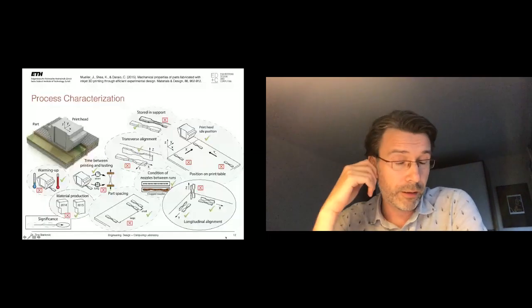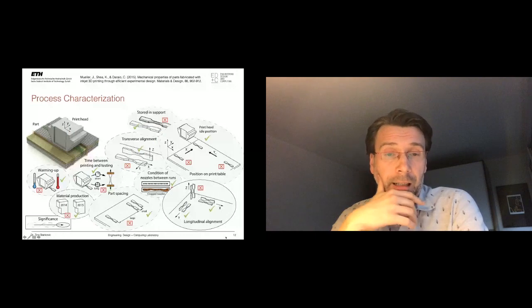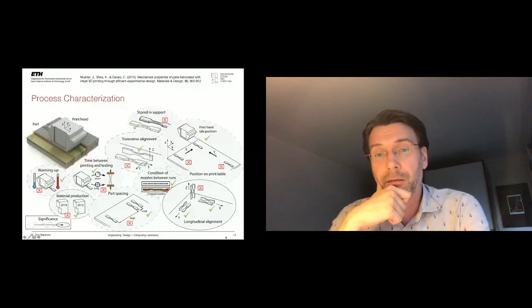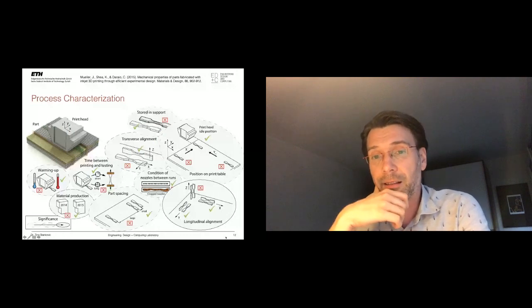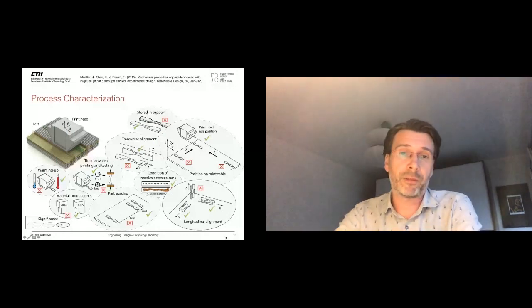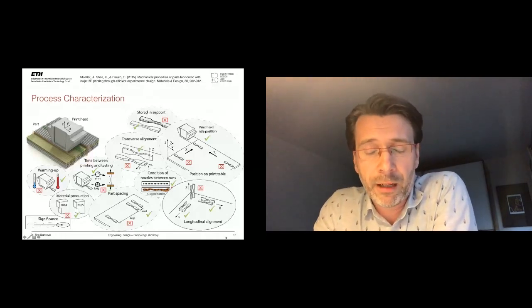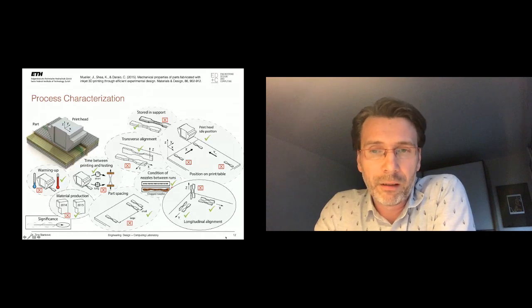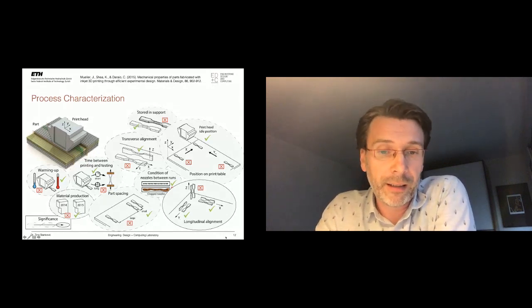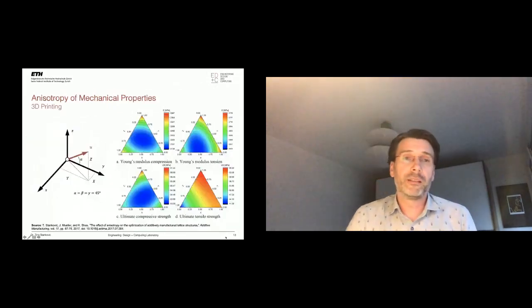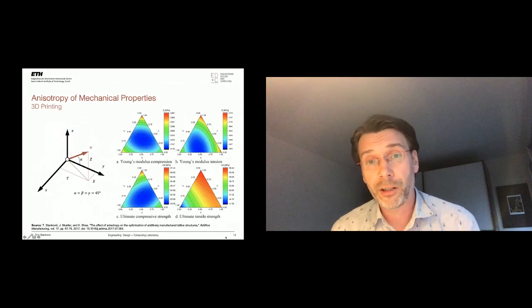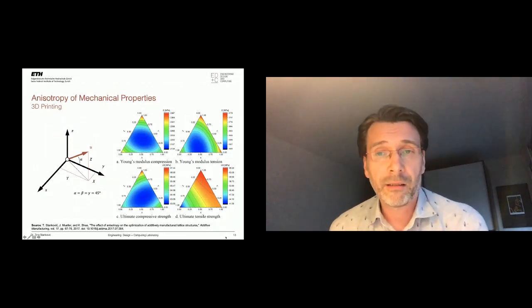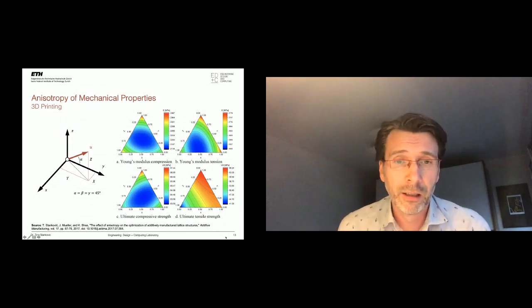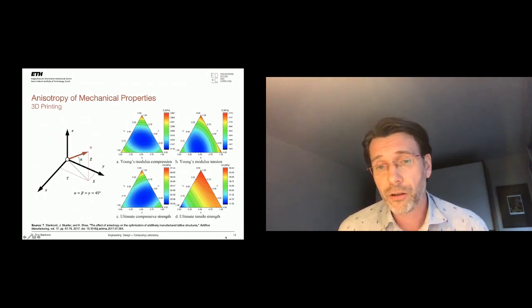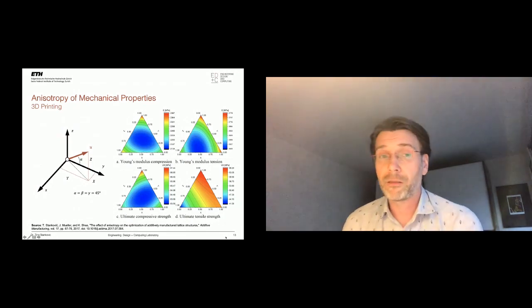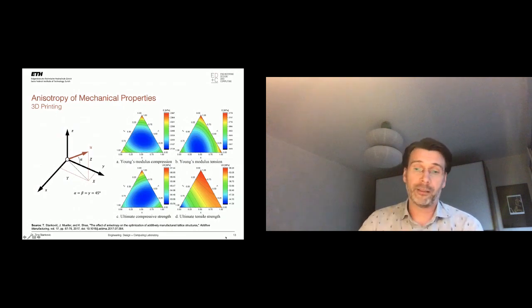And as I introduced on the 2 slides before, I was talking about characterization. So there is process characterization. We already know that many different effects have negative effects on the parts that we print. In this particular slide, done by one of our colleagues, the alignment of the bar during the printing had a significant effect on the material properties, which yielded anisotropic mechanical properties with respect to the orientation of each of the bars printed. And we captured this in a mathematical model, in which we showed Young modulus for compression, Young modulus for tension, and ultimate compressive strength, ultimate tensile strength with respect to the orientation of each bar in a lattice structure. However, that's not enough.